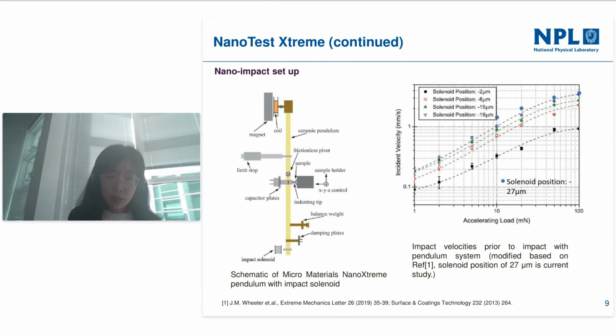And on the right side of the image, together with a previous study, the range of speed achieved with this type of setup is by combining the acceleration load and acceleration distance. So we can achieve up to 0.5 millimeter per second of speed.